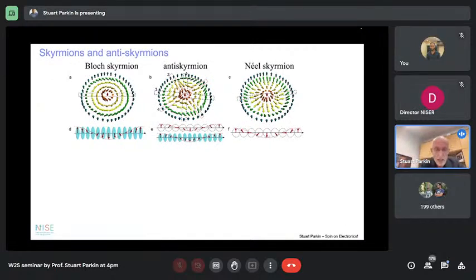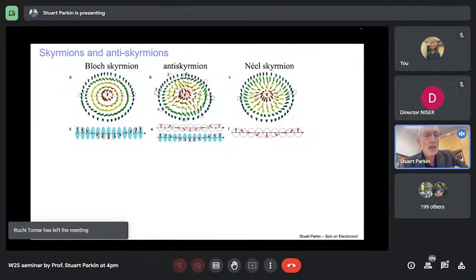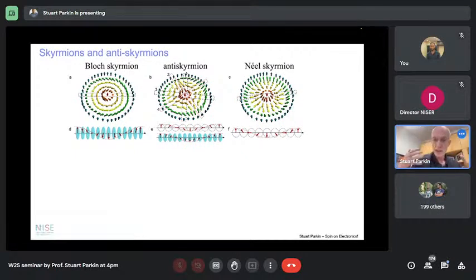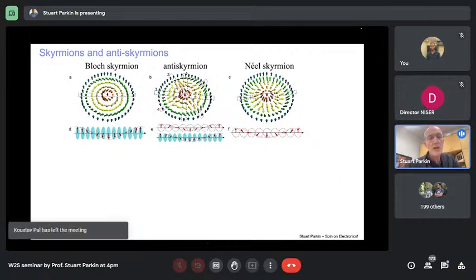So the idea is you take a material which is perpendicularly magnetized. If you have this chiral exchange interaction, you can form, for example, these 3 distinct types of skyrmions. The material, which otherwise would have a uniformly magnetized magnetization, under some regions of field and temperature will break up, so its state will consist of an array, typically hexagonal, of these circular objects. And the one that was discovered originally by Christian is this Bloch skyrmion on the left.